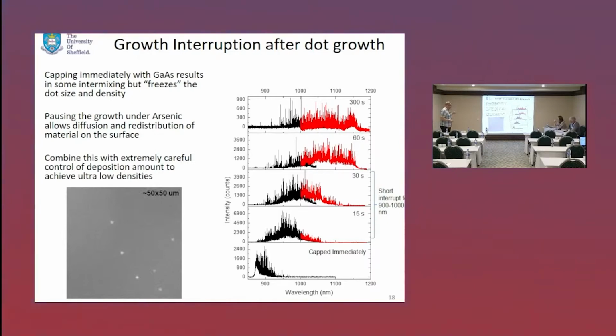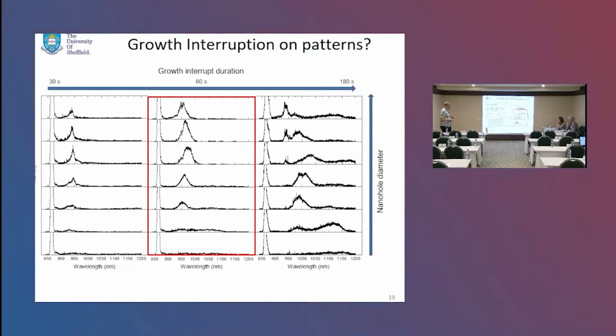If we combine that technique with extremely careful control over the amount we deposit, then we can actually end up with ultra low dot densities. So this is not an SEM image, this is photoluminescence imaging still, but this is a 50 by 50 micron image and we have 6 dots. So if we wanted to make a circuit, this is fine, but if you wanted to make lots of them, then you start to have a problem. So this is still why we want to control the position.